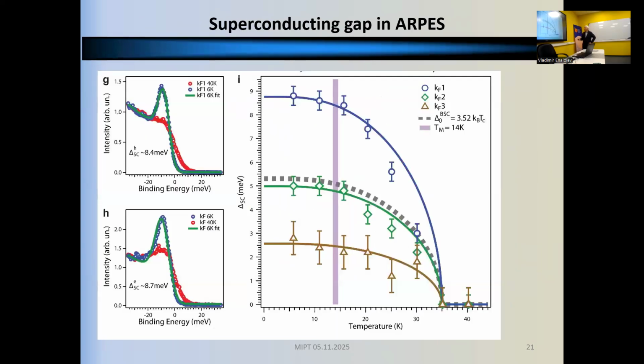From ARPES measurements, the question we wanted to understand was how the magnetic ordering affects the superconductivity. From these ARPES measurements, we measured the superconducting gap, and three gaps were noticed. They developed smoothly with no features exactly at the temperature of magnetic ordering.